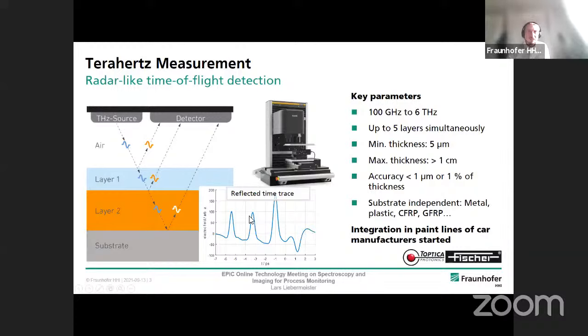So from the distance of those peaks, we can then back calculate the thickness of the individual layers and thereby measure up to 5 layers simultaneously. The minimal thickness we could measure was 5 micron, and the accuracy is much below 1 micron or 1% of the thickness. And of course, since this measurement is fully in reflection mode, it does not matter what's below your car paint. So it could be metal or plastic or anything.